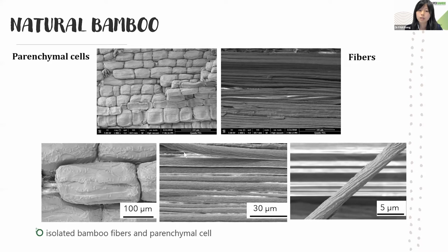We can say that the fiber is more like a solid, but the parenchyma cells are more like a capsule shape. Which means the capsule shape will give you larger space for compression, but the fibers will provide more strength. Some researchers also did research about the tensile strength of these fibers. They found that the maximum tensile strength of these fibers can reach around 2.2 gigapascal, which is quite high. Compared to the known tensile strength of bamboo, which is around 100 megapascal, this means there is a larger space that we can improve for natural bamboo.